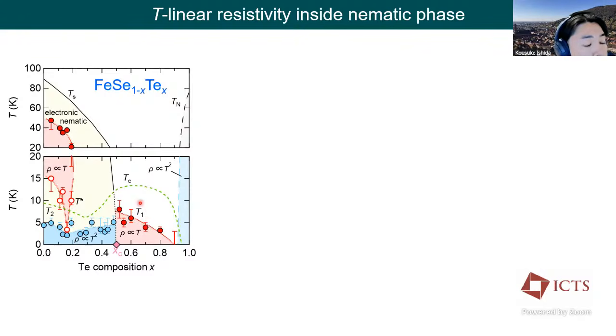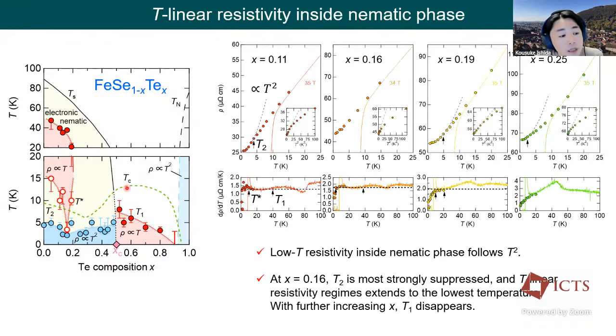So, for now, let's see the detail of this phase diagram. First, inside the nematic phase, the resistivity follows T-square at low temperature for all compositions. And at x = 0.16, the onset of T-square resistivity is most strongly suppressed, so it has a wide T-linear resistivity window. But this T-linear resistivity regime in the nematic phase disappears with increasing x from this x = 0.16.